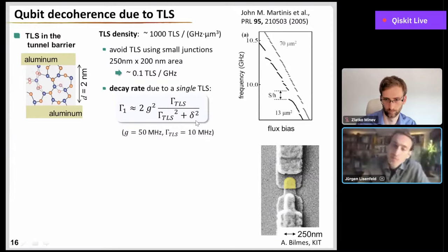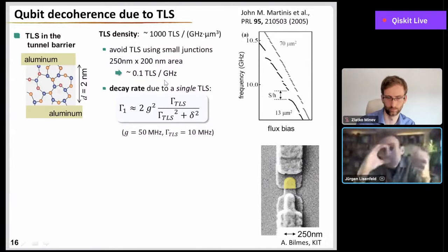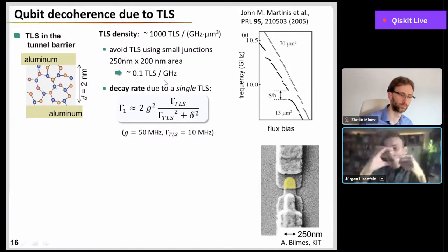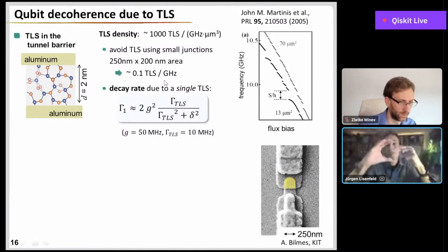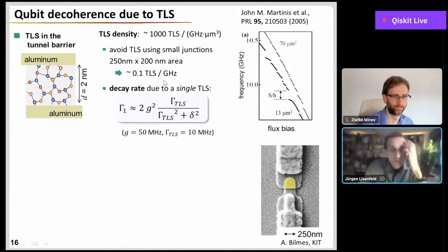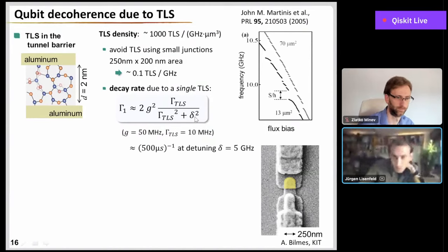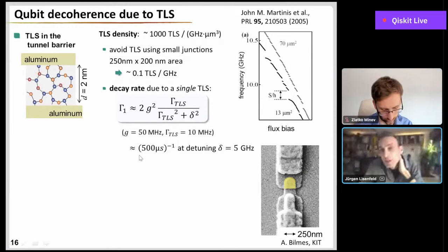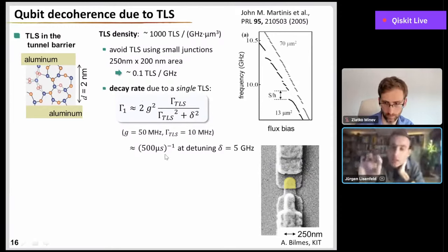Now, if you have 0.1 TLS per gigahertz, this means the average spacing between defects would be like 10 gigahertz. And so then the best detuning to the qubit would be like 5 gigahertz if you put it exactly in the middle. And if you now just put the 5 gigahertz detuning there and the other parameters, then you find that the qubit T1 time is already reduced to only 500 microseconds, only due to the single defect, more or less detuned far away from the qubit.